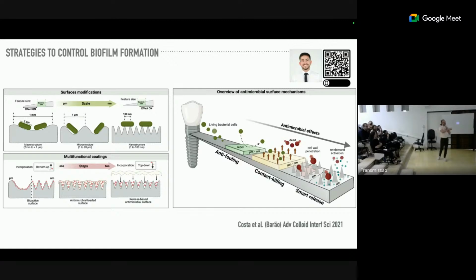We also have a contact killing mechanism. For example, we have some surface that is nanostructured. The surface is very pointed. When the bacteria adhere onto the surface, the membrane of the bacteria can be perforated. So it's a contact killing mechanism. But the contact killing mechanism by itself is not so interesting, because we already see in the literature that if you have a dead bacteria on the surface, the bacteria is there, it has not been removed. We might have more live bacteria adhering to these dead bacteria.